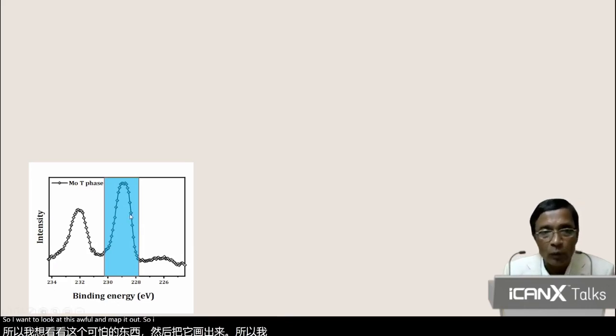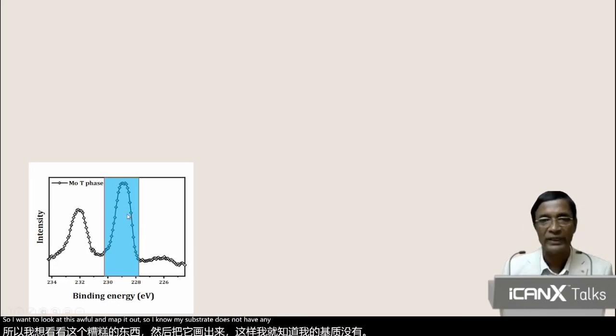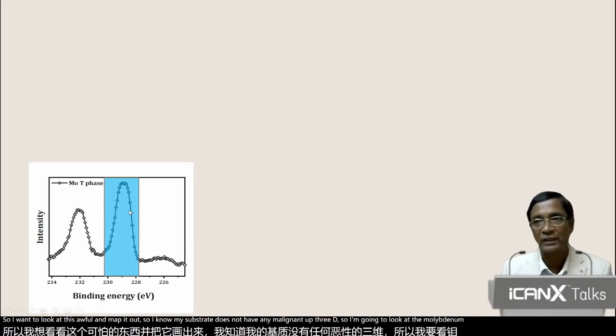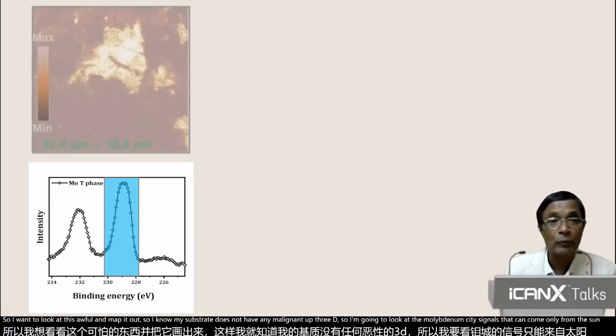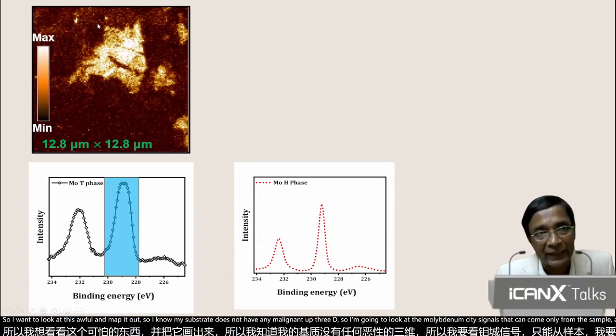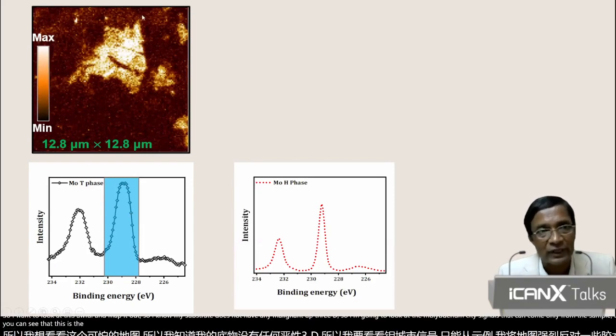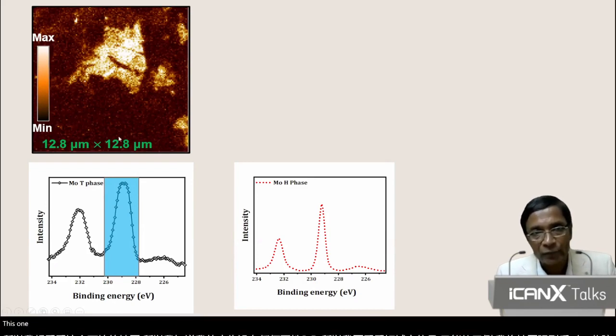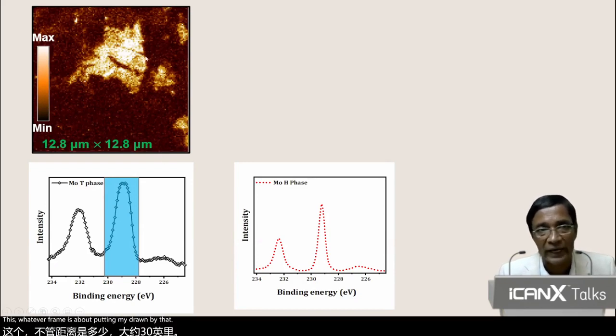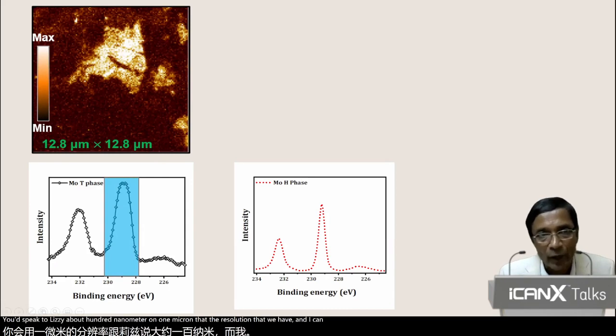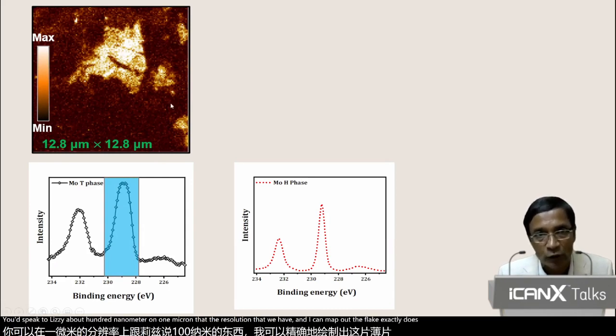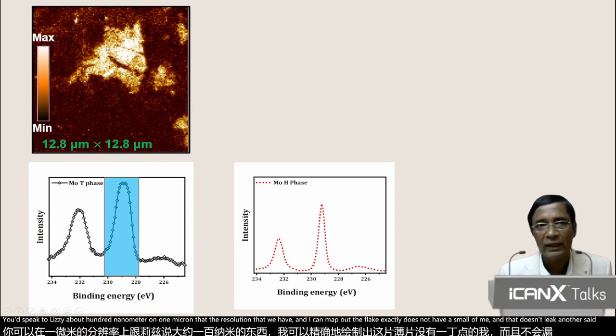So I want to look at this sample and map it out. I know my substrate does not have any molybdenum 3d, so I'm going to look at the molybdenum 3d signal that can come only from the sample, and I'm going to map that intensity. As soon as I do that, you can see that this is the substrate where molybdenum is not there, and this is one flake. This entire frame is about 13 micron by 13 micron. Each pixel is about 100 nanometers, 0.1 micron. That's the resolution that we have, and I can map out the flake exactly. There's another smaller flake, another flake, another flake. That tells you how molybdenum 3d is distributed on my substrate.